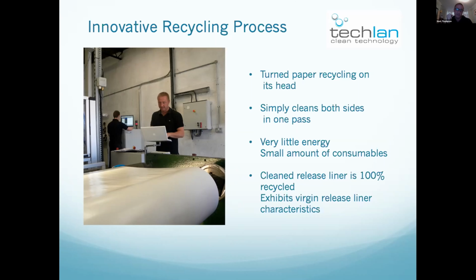What we do is we take the release liner, we clean it on both sides in one pass. We use very small amounts of energy and consumables during that process. And what we end up with then is a 100% recycled release liner that still exhibits its prime grade characteristics. We don't destroy the base paper. We don't destroy the release coating. We don't recoat. We clean the product, allowing it then to be reused.